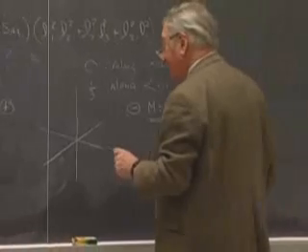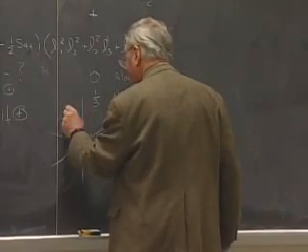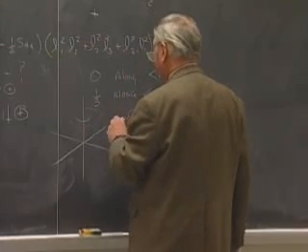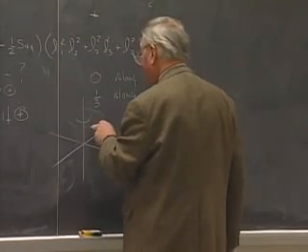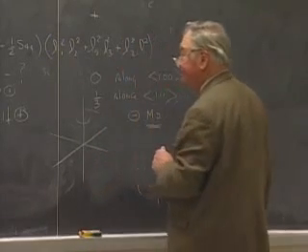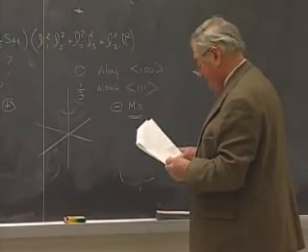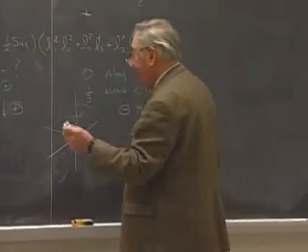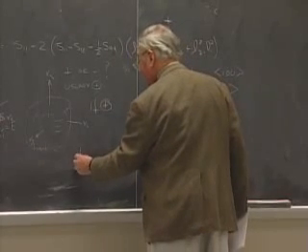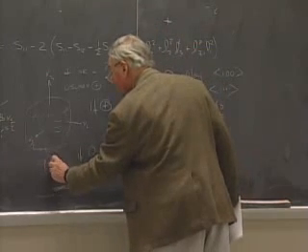It looks like a surface that has indentations along the 111 direction, so it looks like something with a dimple in it. There is a final case, which is not realized for any material that I know of. If that term is 0, then it's isotropic.